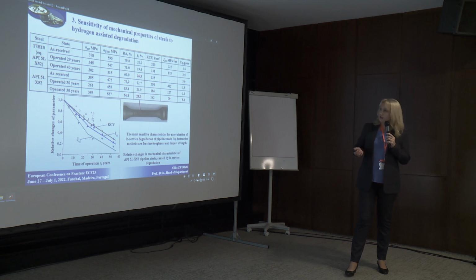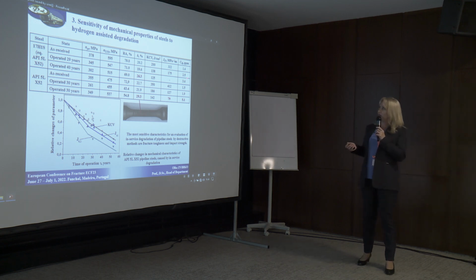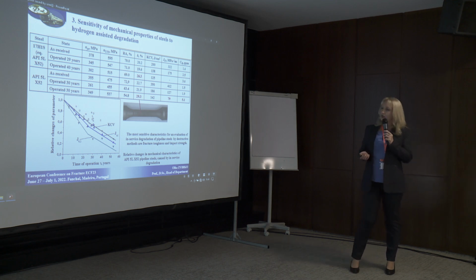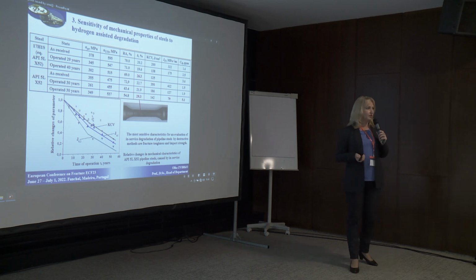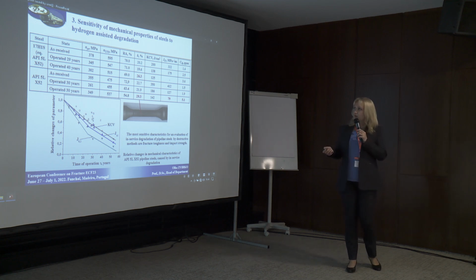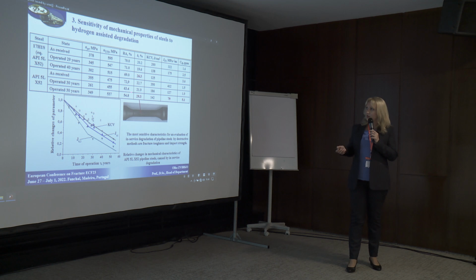Here the presented data show mechanical properties of pipeline steels after operation and also in the as-received state, and also residual hydrogen concentration. The main features of in-service degradation of pipeline steels are a significant decrease in plasticity, mainly in reduction in area, and also in brittle fracture resistance, impact strength, and fracture toughness.